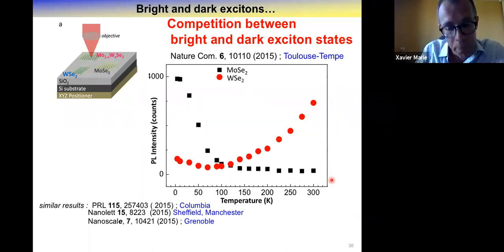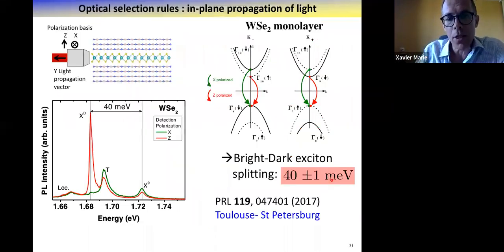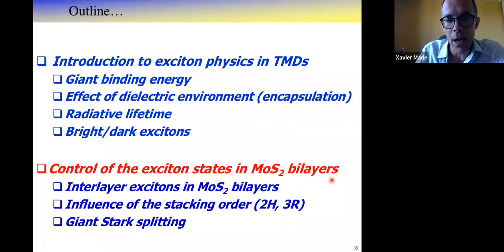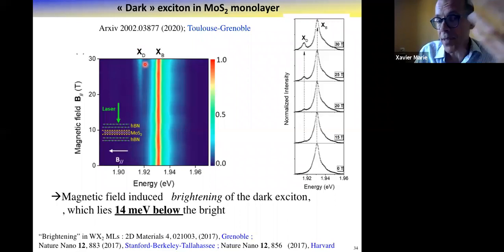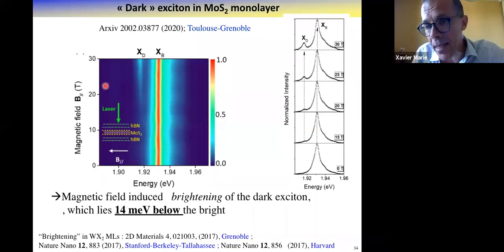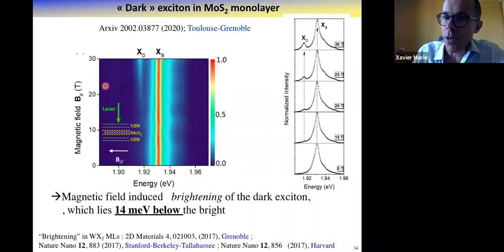So the open question at the moment is, though the dark state is at low energy, why you have this behavior for the temperature? And you see, the problem is we believe that the dark exciton has a rather low oscillator strength. You need very high field to observe it. And even when you observe it, its intensity is much weaker from what we see for WSe2 or WS2 when we have brightening, though in both cases, the dark exciton is at low energy. So the interpretation is open.